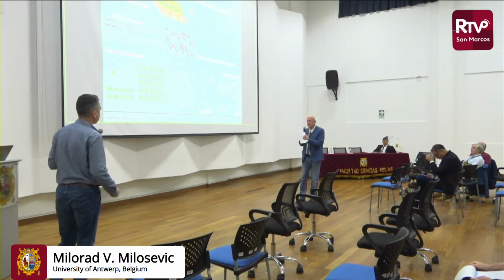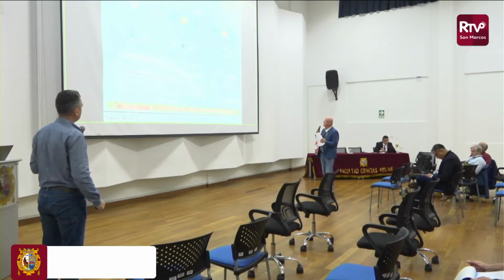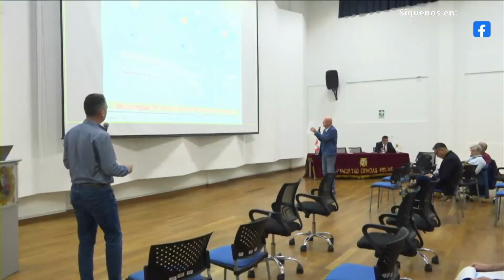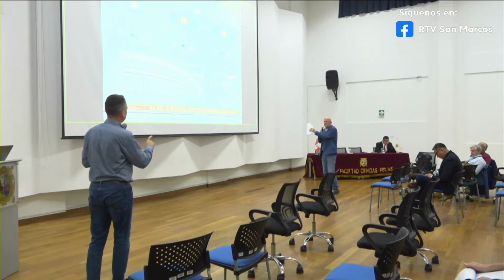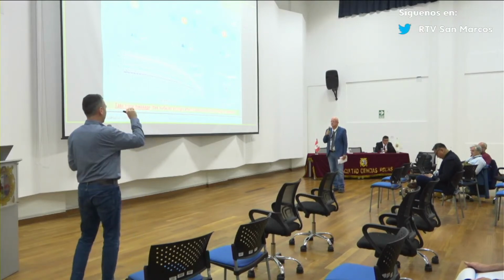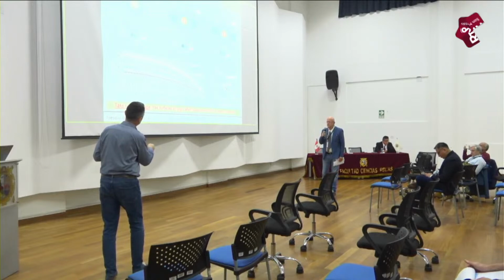I have a question. Magnesium diboride in 6 layers. You showed a plot with the gap versus temperature. Yeah, this one. And we see that the two gaps don't vanish at the same temperature. Where's the theoretical calculation? The experimental one is kind of surprising. This is the gap extracted from ARPES. In ARPES, they're just following one particular place in the spectrum, what they see there as a function of temperature. So this is not really the gap. That's why I added this dashed line. The purple dashed line corresponds to this experiment, and if you see, it actually goes down. So it's just following a particular direction in the electronic structure.